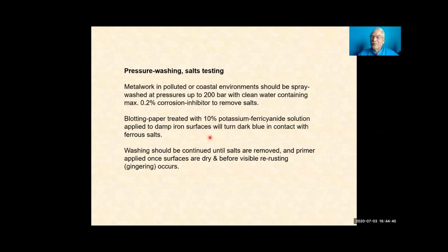dark blue. It's very, very effective, and you can then continue to wash until further tests show that there is no further ferrous salts. Actually, this is so sensitive, you'll always find ferrous salts, so eventually you have to just put the paint on, because you know that there's still a residue of ferrous salts there.